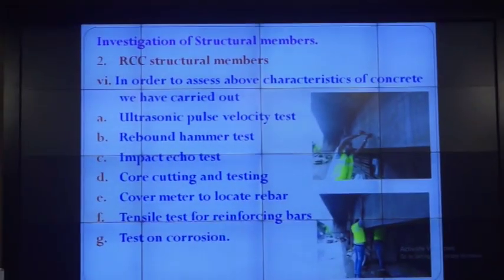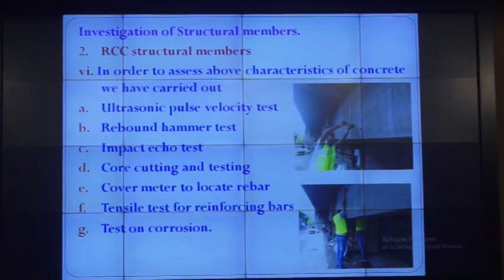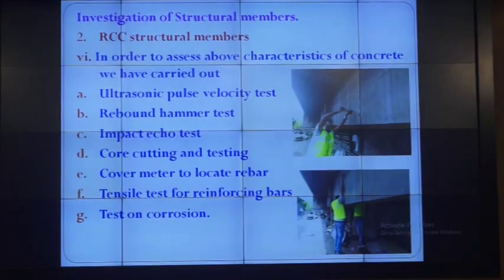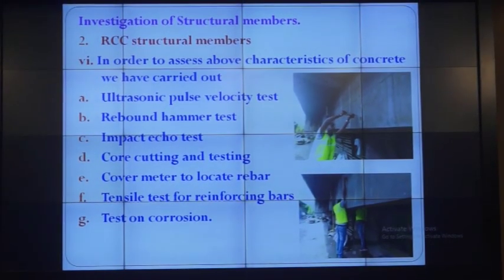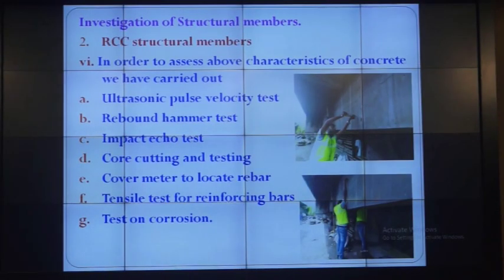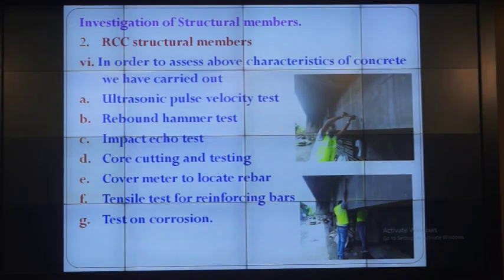As I said, in order to get those characteristics, I have already told you: ultrasonic, rebound hammer, impact echo, core cutting, testing, cover meter, tensile test for reinforcing bars, and test on corrosion. Whatever I have just mentioned, the same thing is here, that has been completed. In fact, some of the bars were also removed from the structural member, about a meter length, and sent for testing to check the tensile strength.